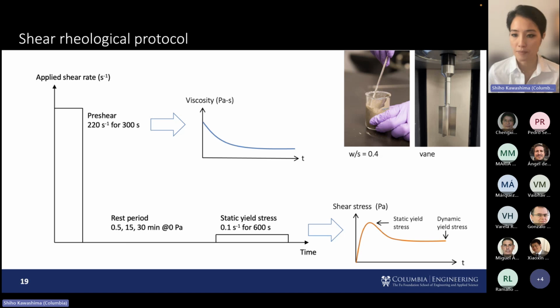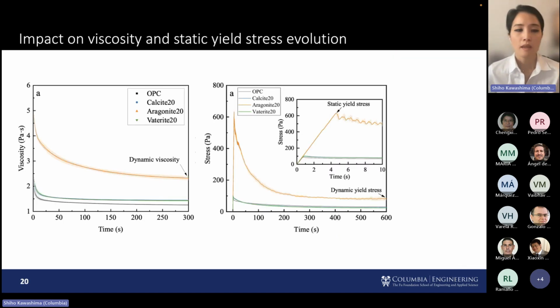We're interested in both of these values. Static yield stress is the stress needed to initiate flow. Dynamic yield stress is the stress needed to terminate flow. So these are the results: impact on viscosity and static yield stress evolution. This is what we obtained during the pre-shear. Compared to OPC, there's some increase with the vaterite and calcite, but then there's a pronounced increase in the dynamic viscosity when you introduce the aragonite. And to mention, all these materials have the same specific gravity, so we can assume that they had the same solid volume fraction. So there's this jump in viscosity.